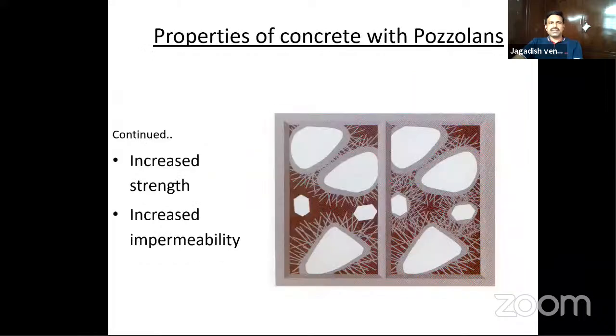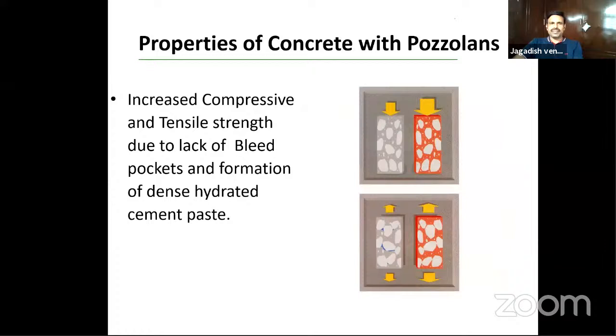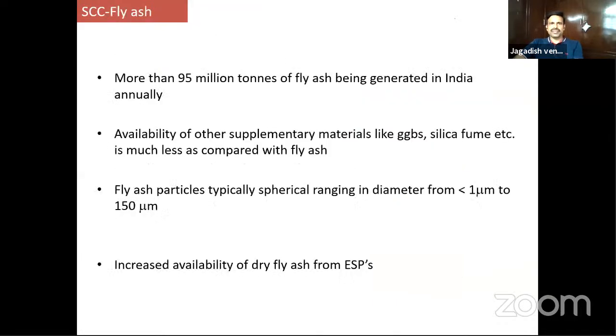This is the typical hydration process, and if you add pozzolan, it will increase the impermeability and it will increase the strength because the pores will get filled with the additional CSH gels. And also it will increase the compressive and tensile strength because you have fewer bleed pockets and a more dense hydrated cement paste in the concrete with the pozzolans.